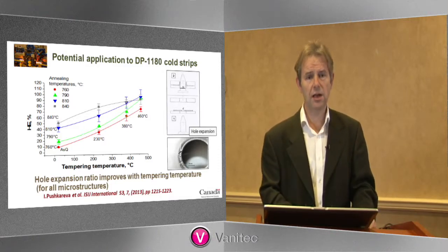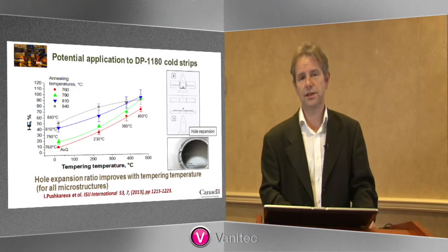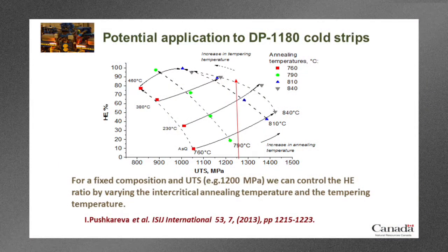This is the reason why high strength dual phase steels are very often tempered. From that you can make what we would call a process map, so a process properties map. In this case, again, I've taken hole expansion coefficient and plotted it against ultimate tensile strength, and we've used the 4 different annealing temperatures. So there's only one composition. I must remind you, this is all done with one composition of steel.